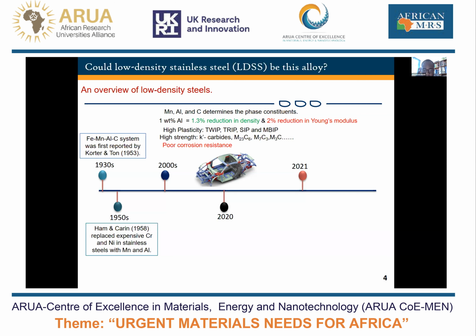The strength comes from the different types of carbides that precipitate within the grains. And some also precipitate around the grain boundaries, but it's more beneficial if the carbides precipitate within the grains. In terms of plasticity, that is even much superior to high strength alloy steels, it is because of mechanisms such as twinning-induced plasticity, then shear band-induced plasticity and microband-induced plasticity.